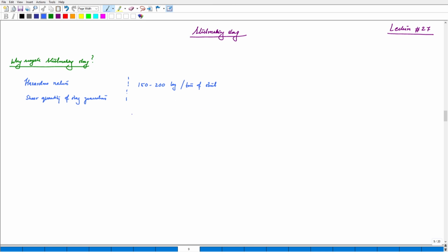What it really means is, if we try to come back to the overall steel production on a global scale, and we try and see per ton, of course, for even each unit of steel making, the slag generation may change, but generally we can say that okay, 150 to 200 kgs, of course it could be more or lesser than this range, but if you look at that quantity and multiply it with the total steel production, we see that this quantity of steel slag is enormous, which is why recycling the slag becomes a challenge because of limited land resources and the hazardous nature of the slag.